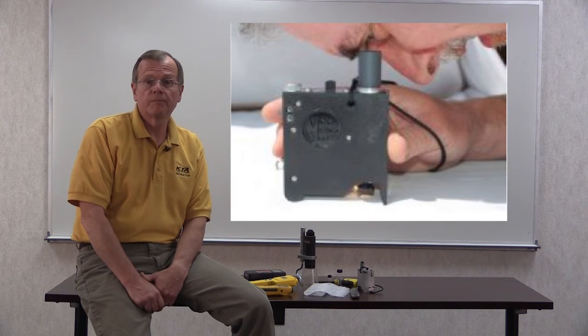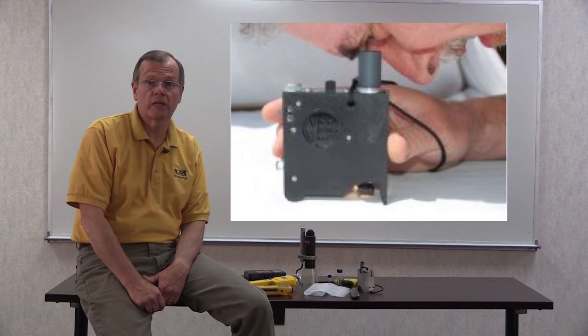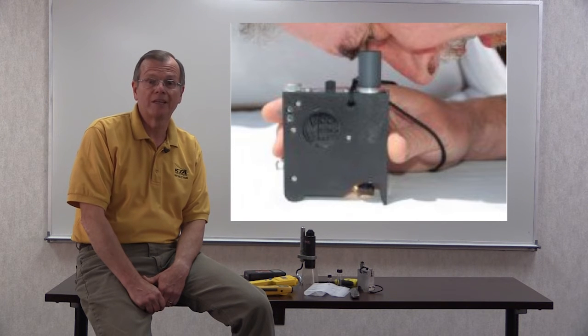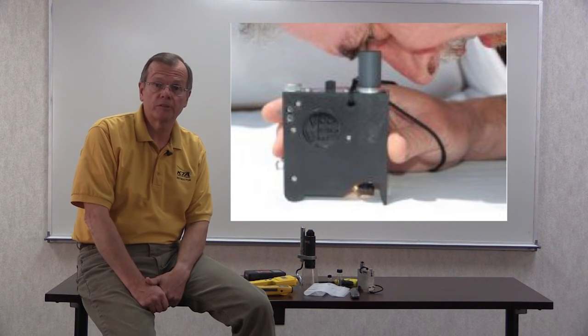The Tooke gauge is destructive. It requires making an incision or groove about the width of a pencil line through the coating film down to the substrate. The Tooke gauge can be used to measure coating thicknesses up to 50 mils.